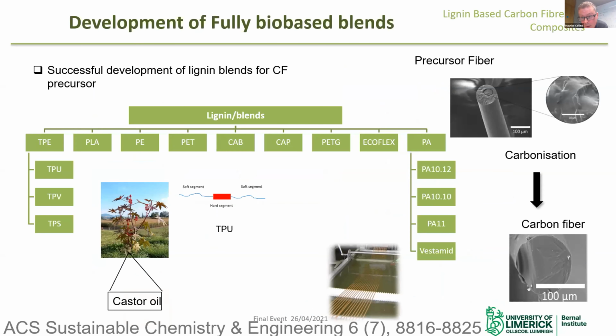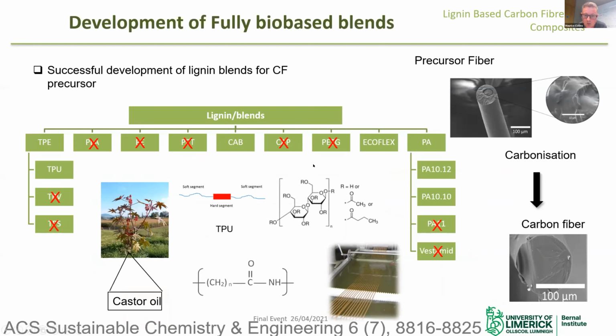And so just to talk about the precursor fibers themselves. So we got 50% or more lignin, and we blended it with all these polymers that you see listed here. These are all bio-based polymers. I X'd out the ones that didn't work. And what I mean by didn't work is that these polymers were not compatible. They were incompatible with lignin. So you can use the Flory-Huggins technique to be able to predict this. But we did the experiments, we did rheology, and we looked at these on a microscope, and we saw that they were incompatible. There was phase separation. And when you get the phase separation, then when you carbonize, the phase that separates becomes a void. So you end up with carbons that are full of voids, which are not suitable for structural applications, but they are really good for functional applications. So they didn't go to waste.